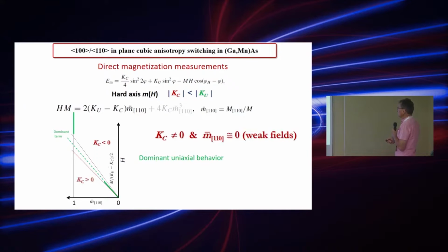Okay, let's move further. And now let's say that there is cubic anisotropy, but it's weak. I mean, it's weak in the sense that we are measuring only weak magnetic fields for which M is, let's say, closer to 0 than to 1. Then we can still forget about this cubic term, because that is definitely much smaller than that. You have to keep in mind that M is always smaller than 1. So a number smaller than 1 to the third power is definitely smaller than M. So we still have a linear relationship, but with a different slope.